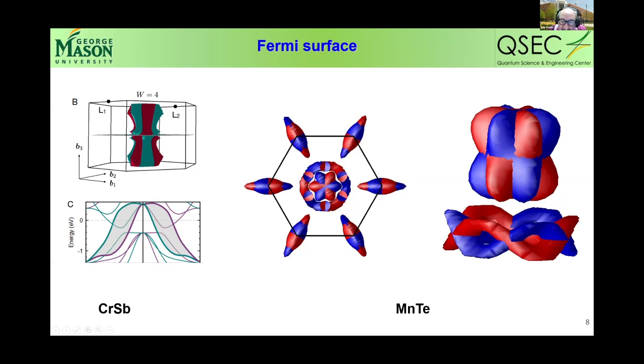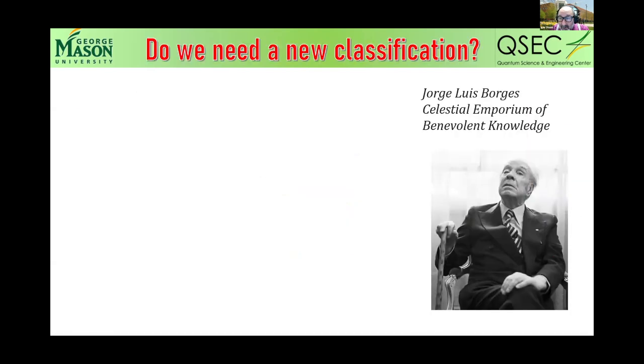You can very clearly observe the symmetry of this object. Each individual spin follows trigonal symmetry, so three axes. Taken together, if you forget about the sign of the spin splitting, it follows six-fold symmetry. And you can see how these things alternate in three-dimensional space. Very interestingly, there is a nodal plane here, and probably Libor will be talking more about the symmetry classification of different altermagnets. And in this particular case, it's imposed by symmetry. There are other similar hexagonal cases when it's not the case, and so on.